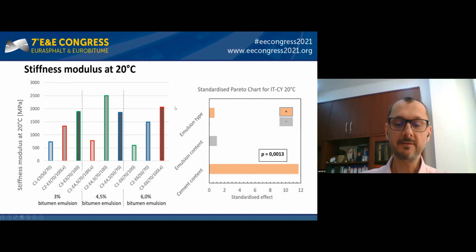And going to the results, as you can see on the left graph, results are ordered in groups of the same amount of bitumen emulsion and by increasing value of the cement content, C1, C2, C3. Generally, we can say that statistical analysis shown on the right graph has proven that the cement amount was the most important factor affecting stiffness modulus of the design mixtures. The results allow us to state that the influence of the bitumen emulsion content and type should be investigated on the mixes containing a smaller amount of cement, where the dominant role of the active filler in the MCA mixture is reduced.